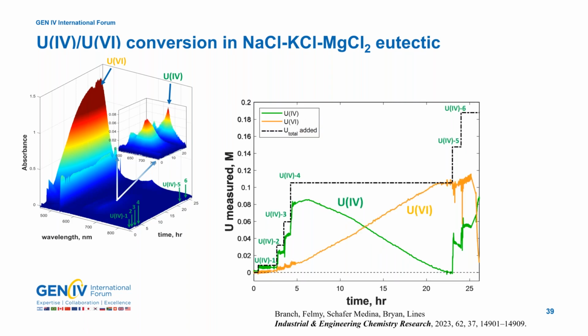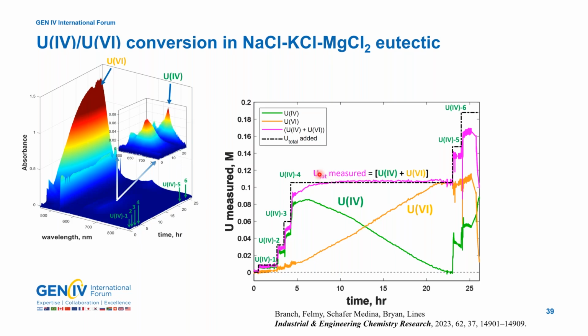And what does it transition to? It transitions actually to uranium-6. And using our uranium-6 model, we're able to calculate and measure the concentration of uranium-6 throughout the experiment. And it grows in just concurrently with uranium-4 dropping out. When we sum up those two species, uranium-4 plus uranium-6, that gives us an inventory of the total uranium in the solution. And we get a really good mass balance throughout the experiment, especially in this middle region here. But if you notice, there's a discrepancy, especially at the transition periods where we add uranium to the system.